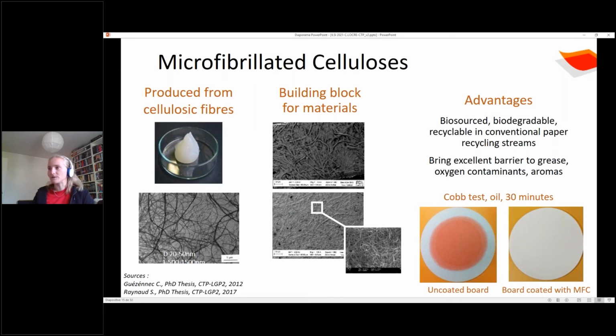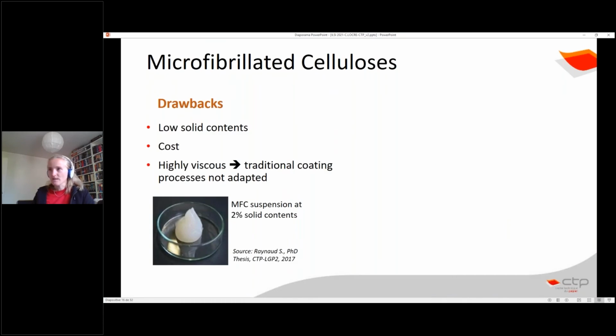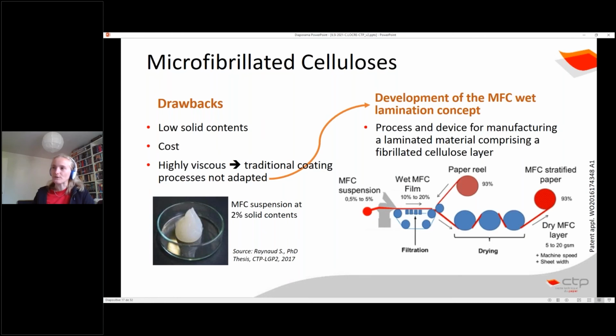And the advantage of microfibrillated cellulose is that it is, of course, cellulose, so a bio-based material, biodegradable, recyclable in a conventional paper recycling stream, like paper and board, but with the additional advantage of bringing barrier. The drawback, however, of this MFC material is that it's manufactured as a gel, so it has a very low solid content, of about 2 to 4%. So the rest is water. But it's highly viscous. So traditional coating processes that are used in the paper making industry are not adapted to apply it on papers and boards, and it was therefore necessary to find a new process, a new concept to be able to deposit this microfibrillated cellulose layer on the paper or board substrate in order to obtain this barrier.